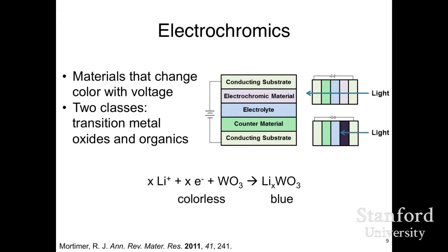So that brings me to electrochromics, which is probably the leader for window applications. In an electrochromic device, there are two transparent electrodes, usually made of indium tin oxide. And on at least one of them, there's an electrochromic material, such as tungsten oxide. If the voltage is applied in one direction, then the tungsten oxide is reduced, lithium comes into it, and in that state, the material is much darker. Although it's not gray or black, it tends to be somewhat blue.